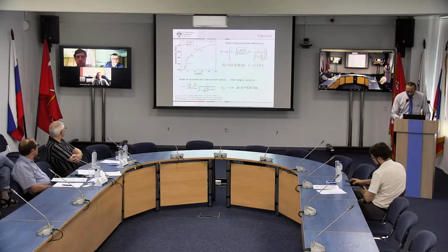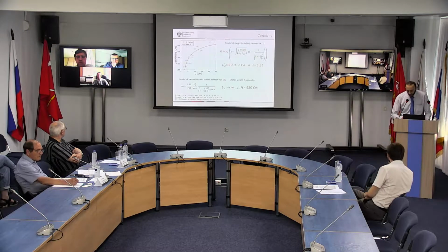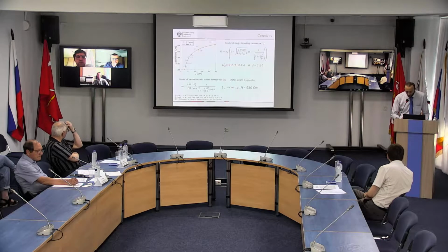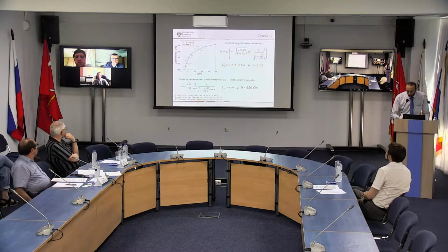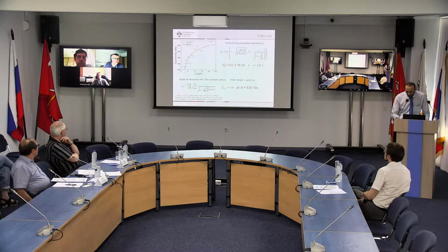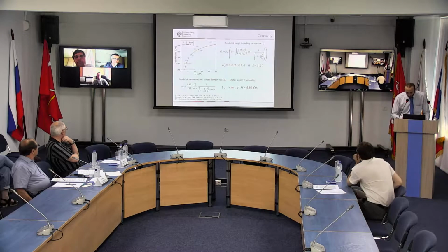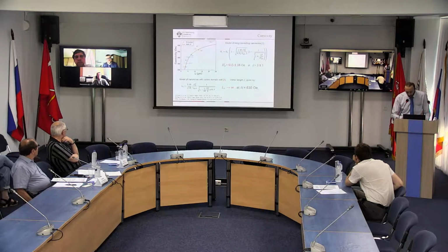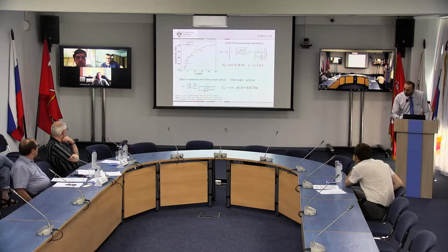Experimental results here show that coercivity increases with length, and according to the model of long interacting nanowires, the macroscopic coercive force can be expressed as a function of length. The best fit to these experimental results, experimental coercivity, using the given equation gives the following parameters, where H0 is coercivity for an infinite individual nanowire, and epsilon is an empirical parameter depending mainly on the arrangement of magnetic nanowires, and is responsible for the energetic barrier between two orientations of nanowire magnetization.